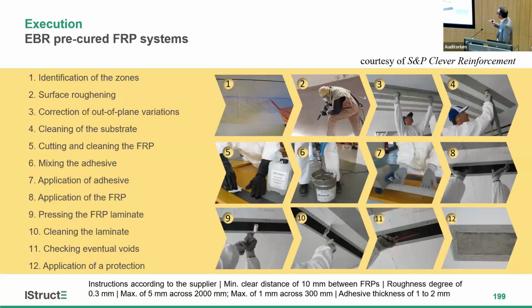Here you can see the different steps that we have to perform in order to apply the external bond reinforcement with pre-cured FRP systems. So we start by identifying the zones to be strengthened, then the surface should be prepared and checked for out-of-plane variations. I include that here, but in the bulletin you have this information, in order to avoid premature debonding failure modes if you don't follow these rules.